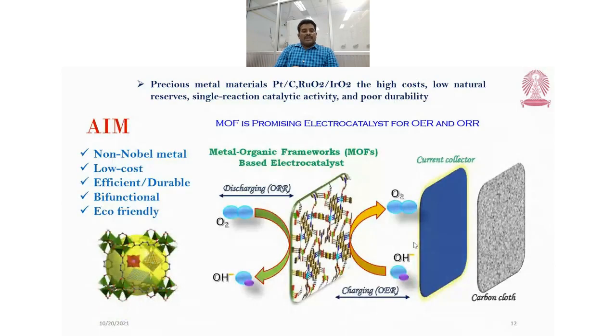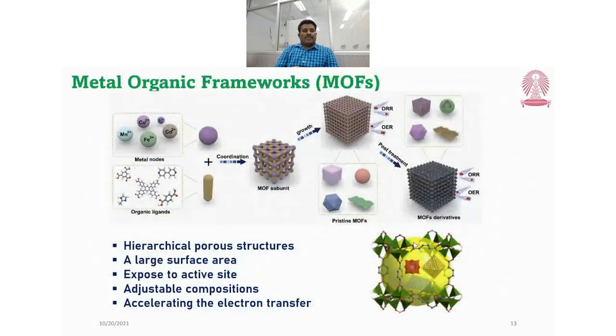MOF is a promising alternative catalyst for the OER and ORR reactions because it is a class of material with a porous crystalline structure. How do we construct the MOF? Metal ions or metal clusters are connected through organic ligands to make MOFs. MOFs have tailorable composition. They have a large surface area to expose the active sites, and they accelerate electron transport during the OER and ORR reactions.